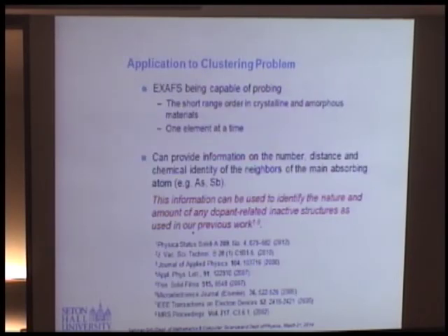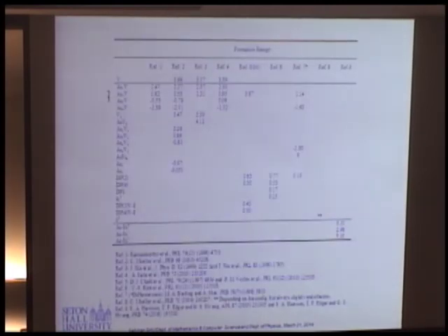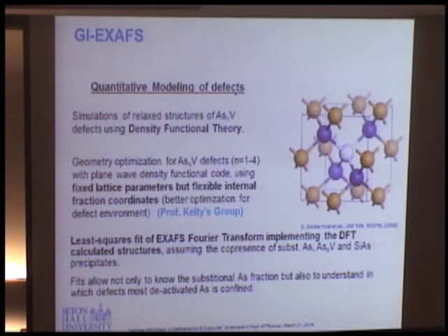What I give them is the structures. So I went to Dr. Kelty's computation, and I know what the possible structures are. All these are possible. At that first stage, just the vacancies are different. I know the activation energies. Can you calculate those structures for me by density functional theory? So I know the structures. I'm going to take my XAFS data from Brookhaven, use your structures in my fits, and tell how many of those are in my structure. And that's what he gave to me.